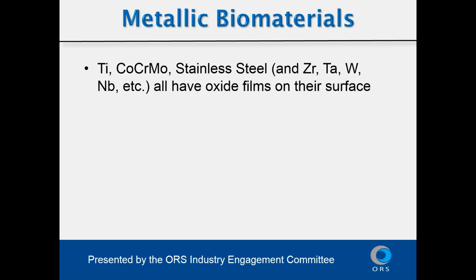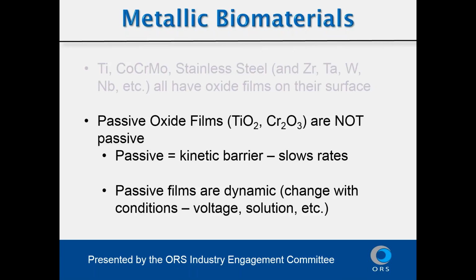So as we all know, metallic biomaterials in orthopedics are primarily the three principal alloy systems of titanium, cobalt chromium, and stainless steel. However, there are these other alloys, zirconium, tantalum, tungsten, niobium, etc., that all have oxide films on their surfaces. These are called passive oxide films, and I give you some examples here of titanium and chromium oxides, but really they are not passive. And when we use the word passive, what we are referring to is they act as a kinetic barrier. They slow the rate of reactions that would normally go on in the absence of the oxide, but because that oxide spontaneously forms, it slows those reactions down.